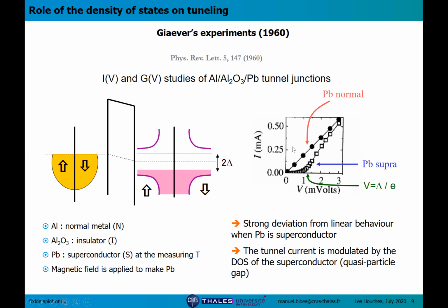And this is very well illustrated by the experimental results. You see the two IV curves, one in the normal state of lead and one in the superconducting state of lead. In the normal case of lead, you have a linear dependence. As you remember, I told you that at low bias, the current is going to be linear with the voltage. But in the superconducting state, clearly there is no current at very low voltage, and only when you exceed a given threshold, which corresponds to the gap of the lead in the superconducting state, are you able to recover a finite tunneling current. So this is a strong deviation from the Simmons and Brinkman model that illustrates the importance of the density of states in tunneling effects.